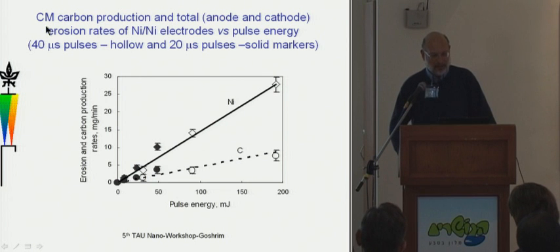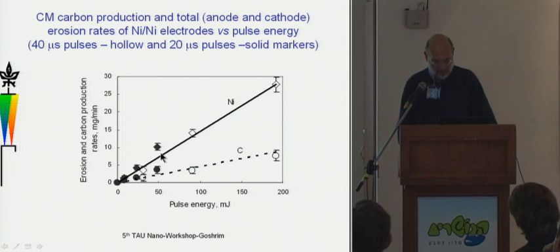This is a case of the contact mode carbon production as well as the total production, in the case of a discharge between nickel electrodes in alcohol. Basically, to determine the carbon production, we take the weight of the powder that's produced, subtract the erosion of the electrodes, and assume that the rest of it is carbon. And again, it's a more or less linear growth with pulse energy.